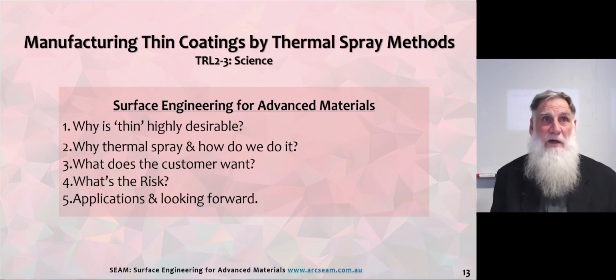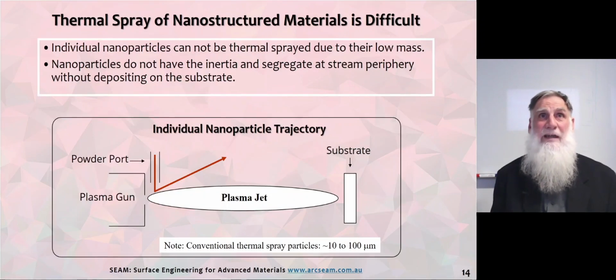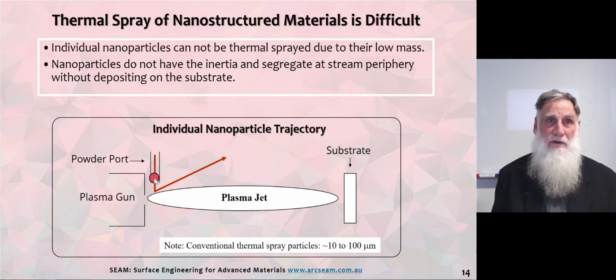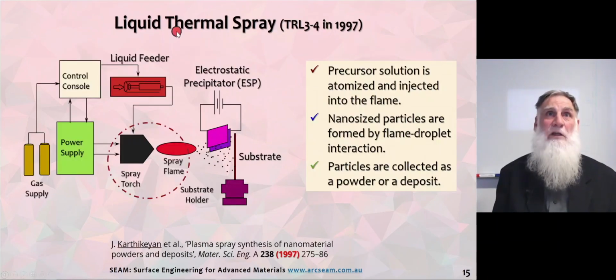So let us go back to our table of contents and address some of these specific questions. Why is thin highly desirable? Thin is highly desirable because it is advantageous to form nanostructured materials. However, individual nanoparticles cannot be thermal sprayed due to their low mass. And what this very simple diagram indicates is that because of their low inertia and their low momentum, they would essentially just bounce off the thermal spray process zone. And they segregate in the stream periphery without depositing onto the substrate. Note that conventional thermal spray particles are of the order of 10 to 100 micrometers in diameter. We get around this issue by a technique which is called liquid thermal spray.